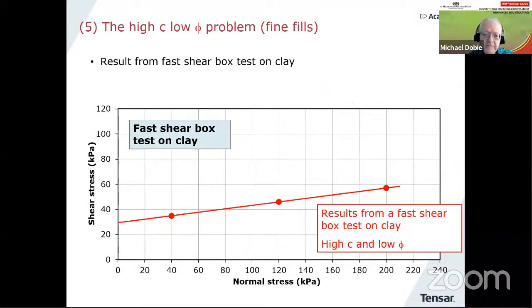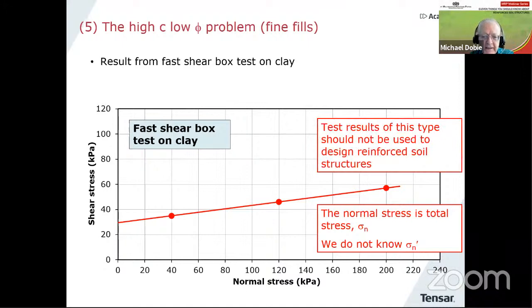What's going on? Well, here's another picture of a shear box. It's just a shear stress, normal stress result, and this is a fast shear box test on clay. You can see we get this very flat line, so we've got the high C, low phi. Why is that happening? The problem is that the three normal stresses there, the sigma n values of 40, 120, and 200, are total stresses. They're not effective stresses. We don't know what the effective stress is during the test because we cannot measure the pore pressure simply in a shear box. So that's the problem, and that's why we cannot use that kind of result to design a reinforced soil structure.